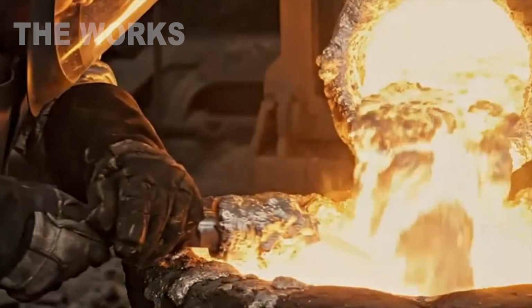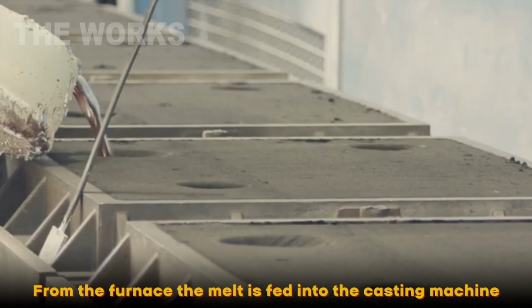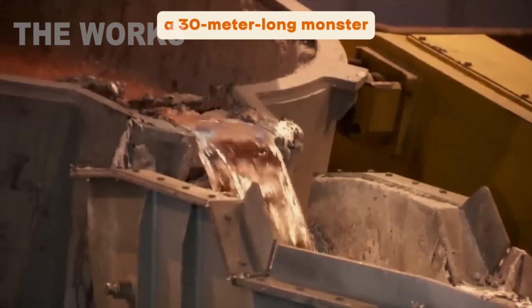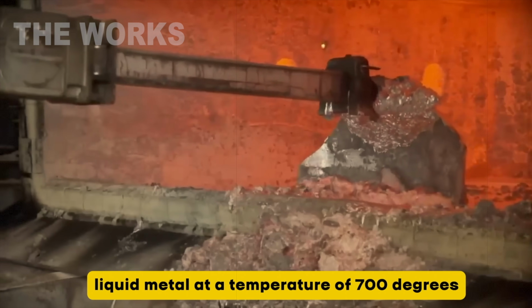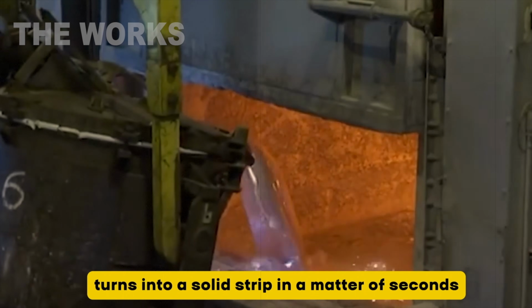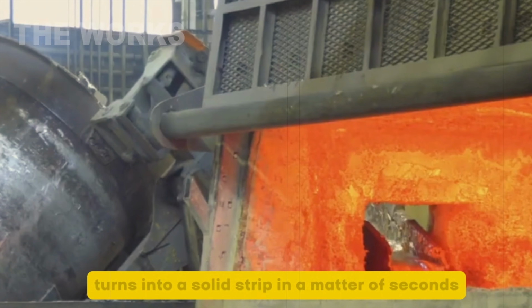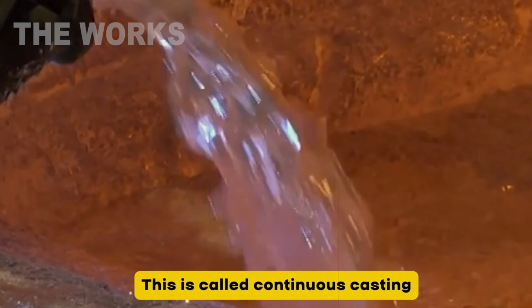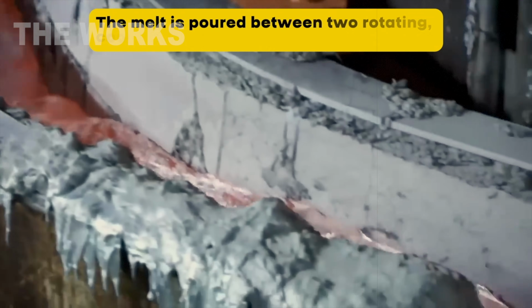From the furnace, molten metal flows into the casting machine, a 100-foot-long monster. Here's where the magic happens. Liquid metal at 700 degrees turns solid in seconds. This is continuous casting. Molten aluminum pours between two rotating water-cooled rolls, 6 feet across.